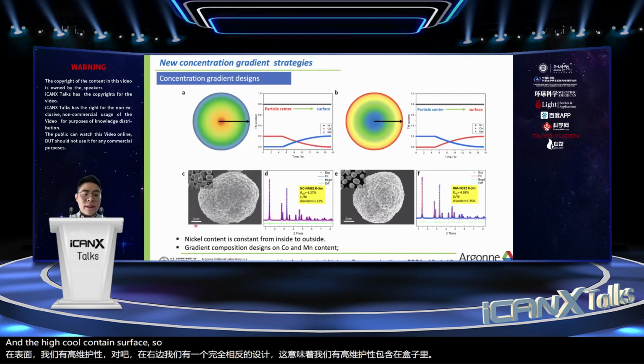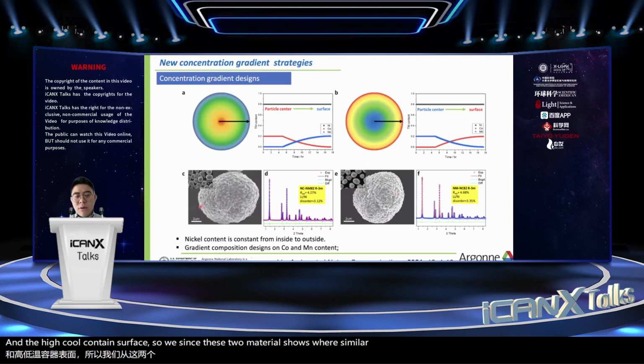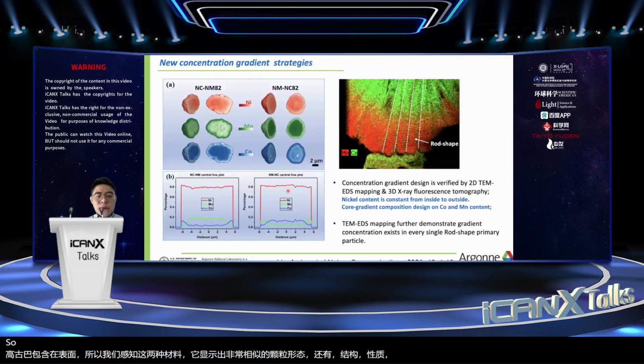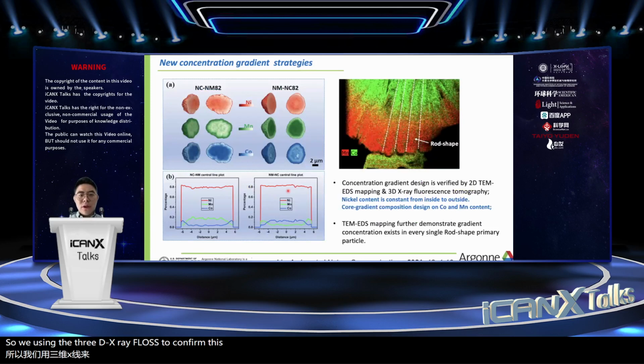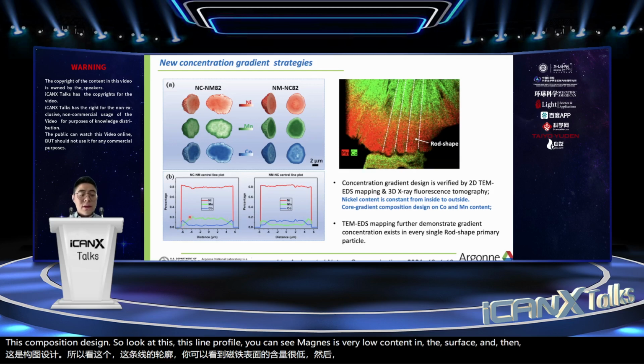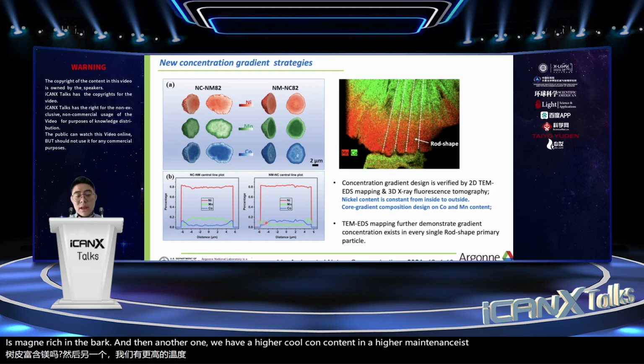So we synthesized these two materials, and they show very similar particle morphology and also structure properties. We used 3D X-ray fluorescence to confirm this morphology and this composition design. Look at this line profile. You can see manganese is very low in content at the surface, and it's manganese rich in the bulk. And in the other one, we have a higher manganese content at the surface and a lower manganese content in the bulk.